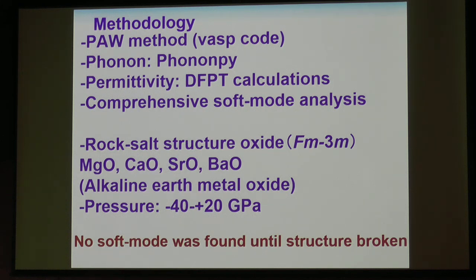Then, to tune the soft mode, we apply pressure in this range. And in the calculated range, no soft mode was found until the structure broke. It's not so exciting.